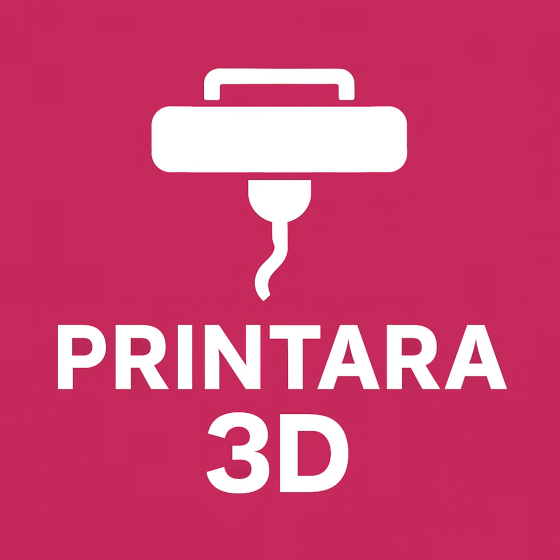An enclosure, why is that so critical? Because without that enclosure keeping the ambient temperature stable and warm, you're almost guaranteed to fight warping and cracking. ABS shrinks quite a bit as it cools down. If it cools unevenly, like the bottom layers are warm but the top layers are exposed to cool air, it creates internal stresses, and the print just pulls itself apart or lifts off the bed. So if you don't have that setup, you're basically fighting physics.